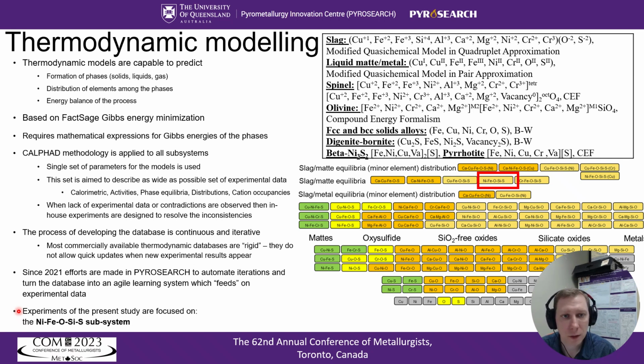To fix the model parameters, we apply the CALPHAD methodology, which requires producing a single set of model parameters, which describes as wide as possible data set of experimental data of various type. A set of model parameters is called a thermodynamic database. During the development of the database, we often see a lack of or contradictory literature data to fix certain model parameters. In this case, we design in-house experiments to resolve the problems. In practice, the process of development of large thermodynamic database is continuous and iterative.